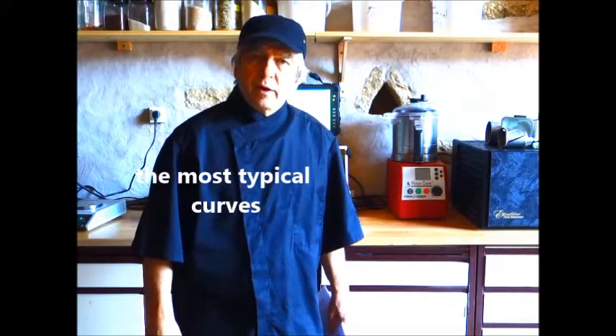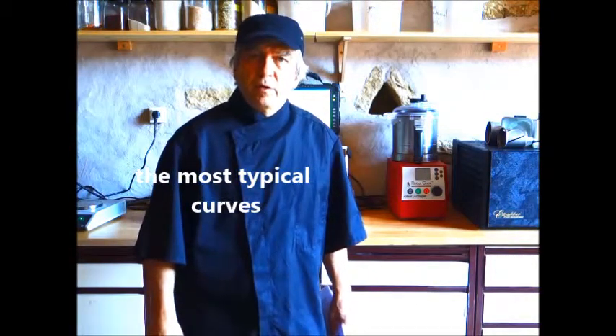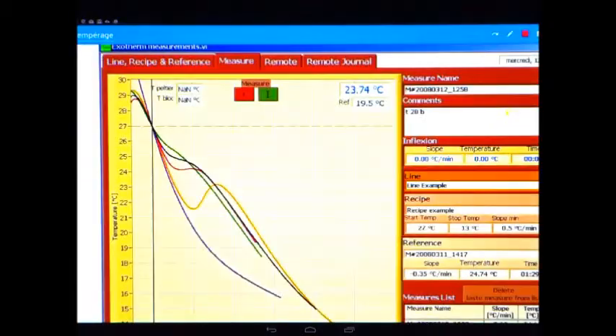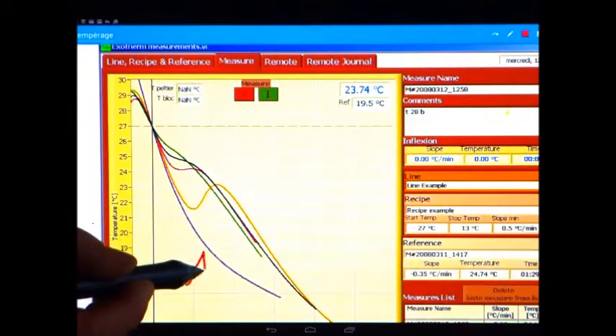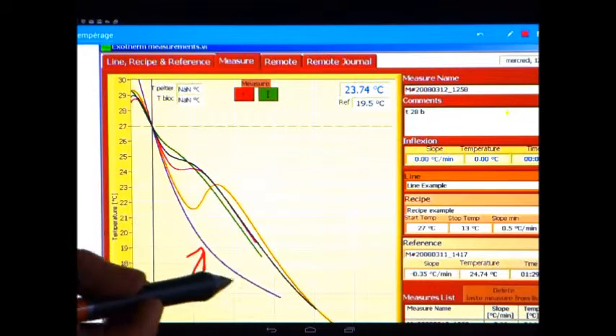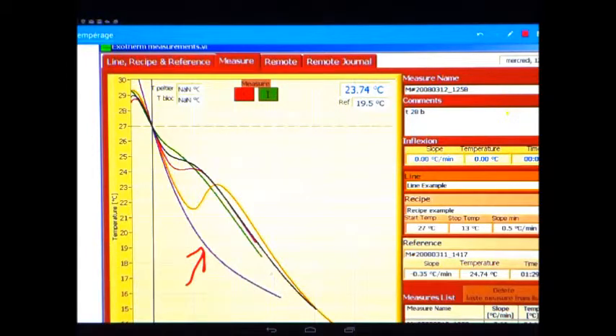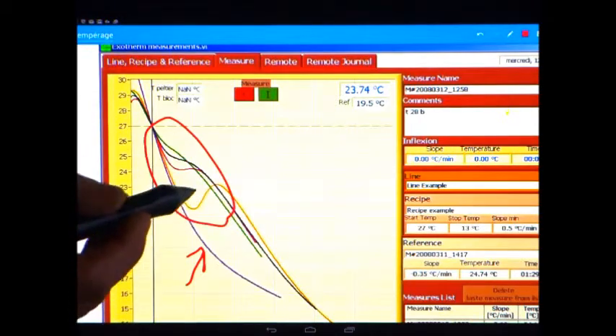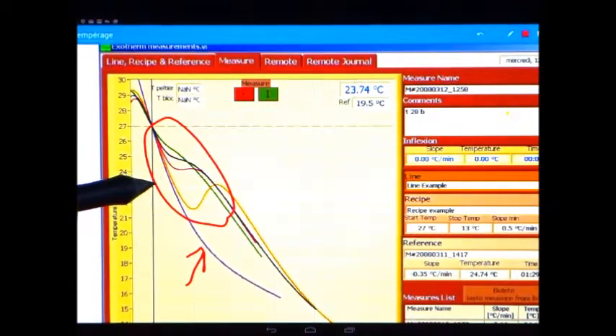Now let's have a look at the most typical curve we may encounter. In this case, we have no inflection. It means the chocolate is not tempered. In all the others, chocolate is tempered. We notice a heat release. The slope of the curve is proportional to the amount of crystals in the step of tempering.